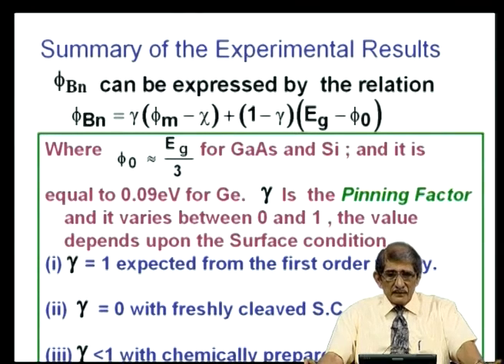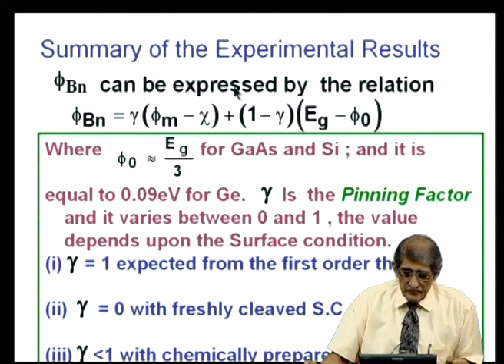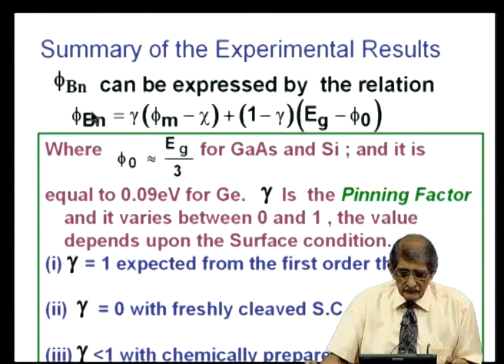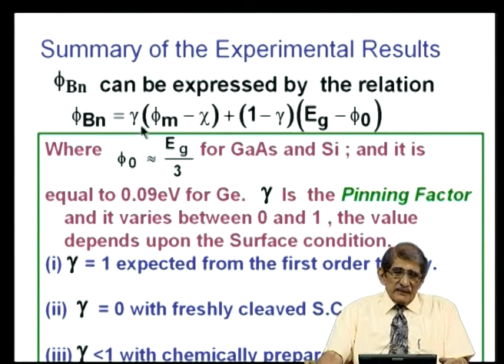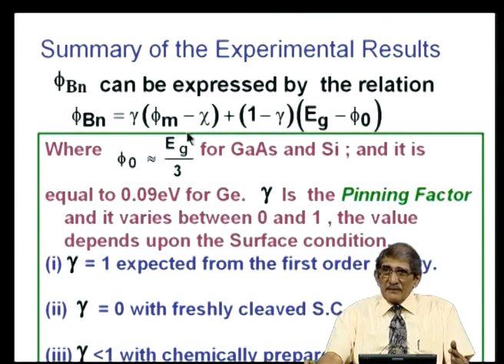But what we have seen is that for metal semiconductor contacts, the barrier height onto the n type material, phi b n, is given by this relationship. Experimentally, one could fit it into this type of curve. Here you can see, when gamma equals 1, what is gamma, we will see shortly. Gamma is between 0 and 1. When gamma equals 1, the second term is 0, and phi b n is phi m minus chi. That is ideal. So, if you vary phi m, you should have a variation in phi b n. But we are not getting that. In some cases, we get phi b n constant, independent of phi m, for freshly cleaved surfaces.